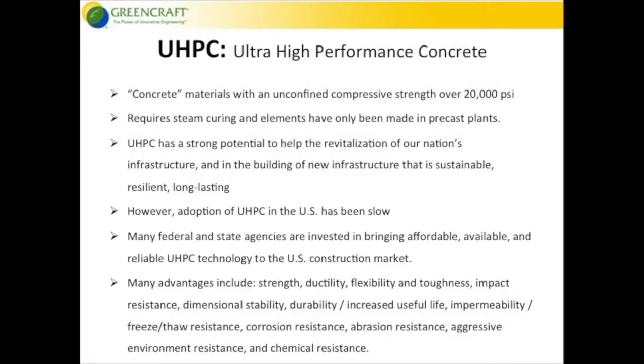We hear a lot about ultra-high performance concrete. Aside from the patching compounds you get in the bag, or the pour backs of bridges and stuff, real structures of ultra-high performance concrete have only been made in a precast plant where you have high temperature curing basically provided by a steam cure room. We have not tested ultra-high performance concrete in the insulated form, but again, I believe that by retaining the heat of hydration, ultra-high performance concrete is possible to cure and make in cast-in-place forms out in the field.